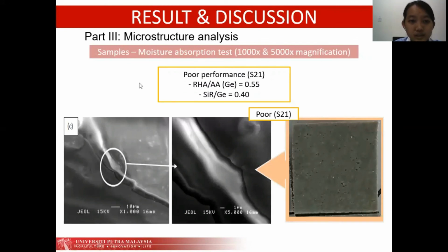And then this is the last sample for the moisture absorption test, with poor performance. The figure shows crack development on the surface of the coating. The cracks and holes form due to non-uniform mixing during hot pressing and consequently increase the water absorption rate. The gap in the coating is filled with water. The water flows into the adjacent matrix by capillary action and forms a damaged zone. In the damaged zone, the water was absorbed quicker than in the undamaged material around the cracked surface.